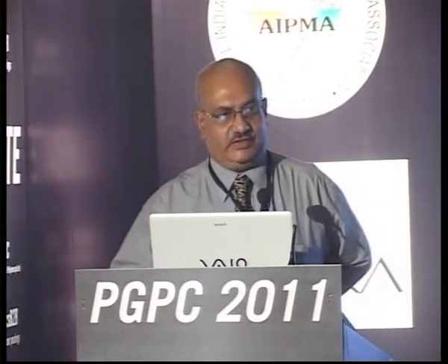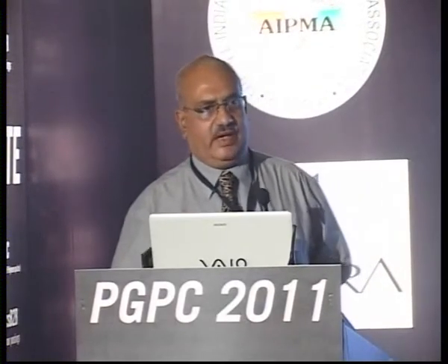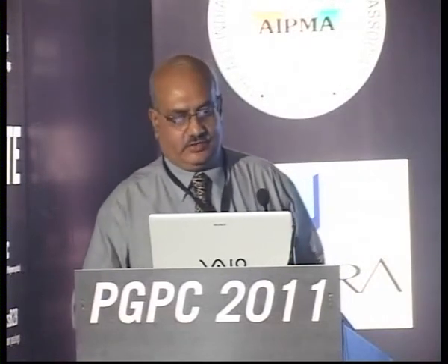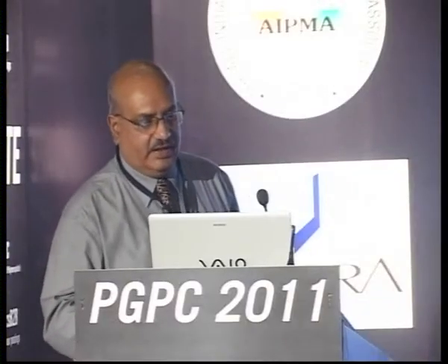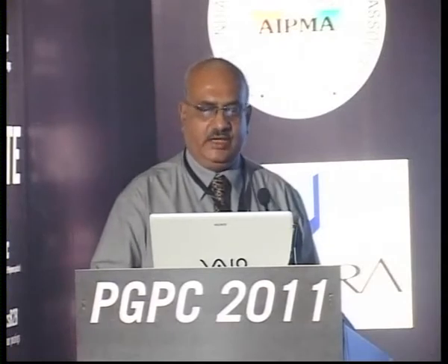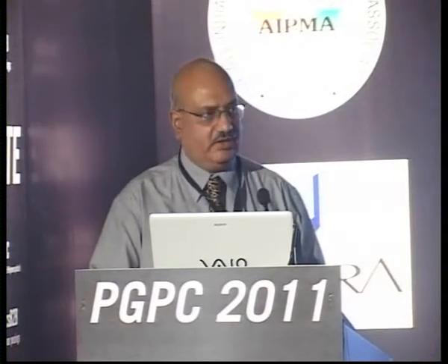So what do we decide from the knowledge of polymer to be colored? Of course, we decide on the carrier, and that affects the colorant selection. Every design factor affects the colorant selection. Actually, the objective of master batch design first is to select the right colorant. So all of these factors affect colorant selection. Second, of course, is the processing temperature. Again, this decides on colorant selection and stabilizer selection. I mean antioxidant selection. Additives present in the polymer. Besides colorant selection, it also decides loading of colorant.